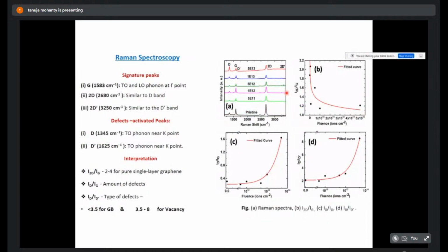So this type of Raman spectroscopy, because Raman spectroscopy gives the exact signature of the defects and the exact signature of the graphene, whether it is produced or not. So that gives about this 2D peak at 2680 centimeter inverse. So that gives the 2D peak, means it is a good pristine sample, like a good graphene sample, and these are the peaks of the D and the G peak, and these are the defect identified peak, and this is the peak corresponds to the stretching bond.